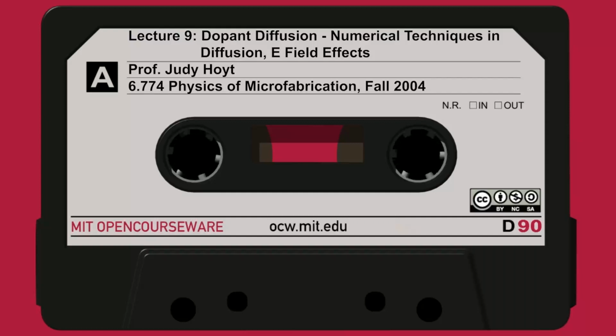Let's go on to slide number 20. And so what we do is we modify Fick's first law, and we modify it in a way that's very similar and almost identical to what we do in our electronics or solid state physics classes. We say that the total impurity atom flux in the presence of both a concentration gradient and an electric field can be written down as the sum of two fluxes. One is F, which is the normal Fickian diffusion flux, given by minus D partial C partial X, plus F prime, where F prime is now the drift flux due to the electric field.